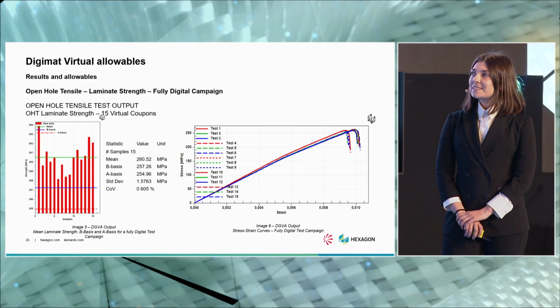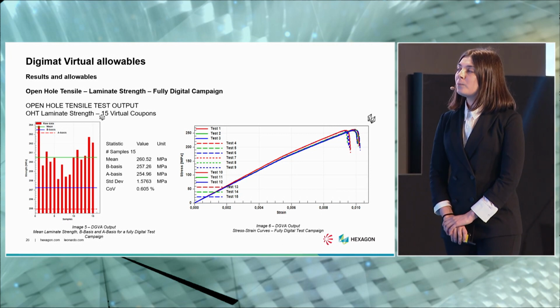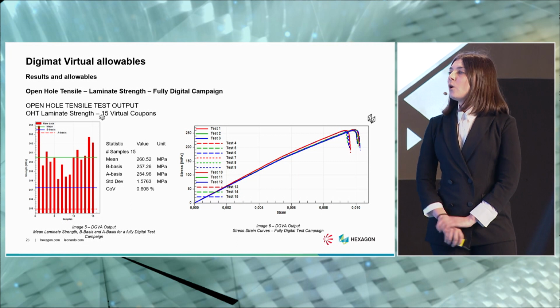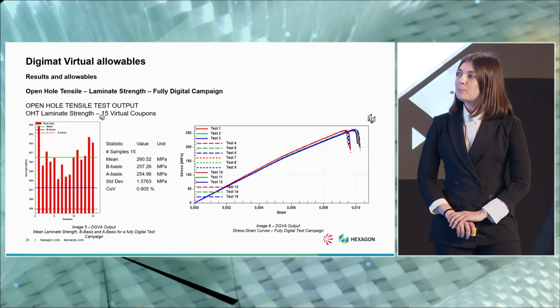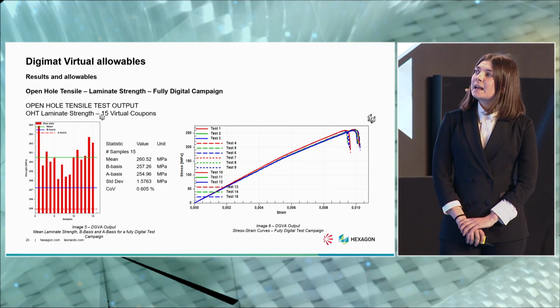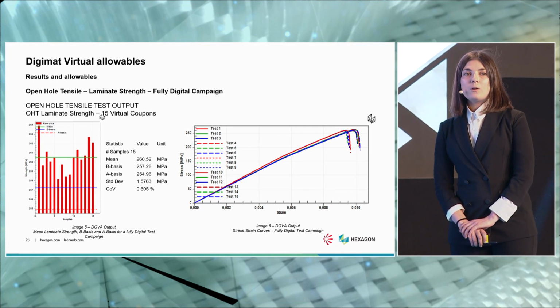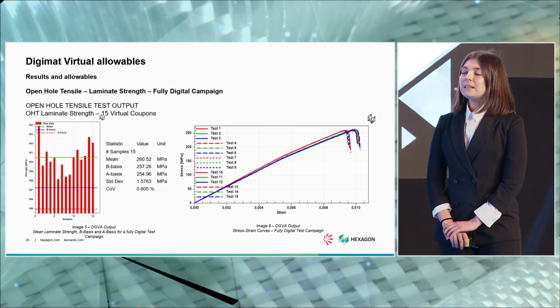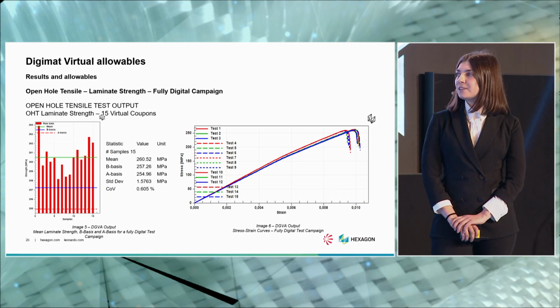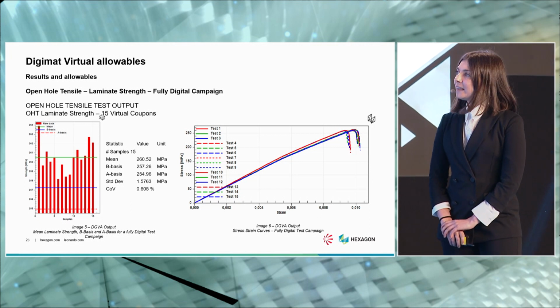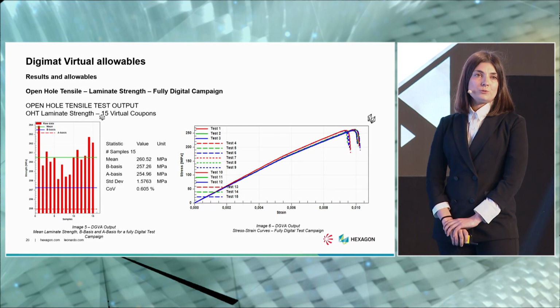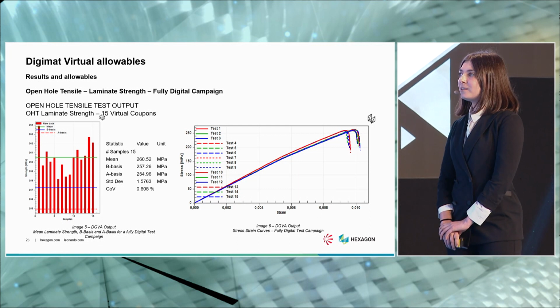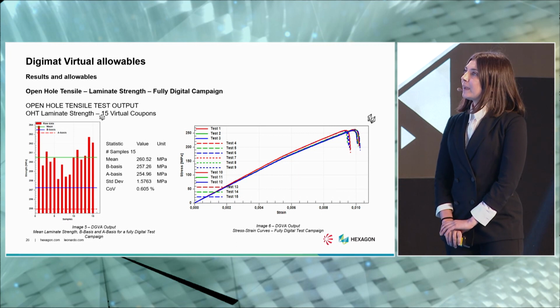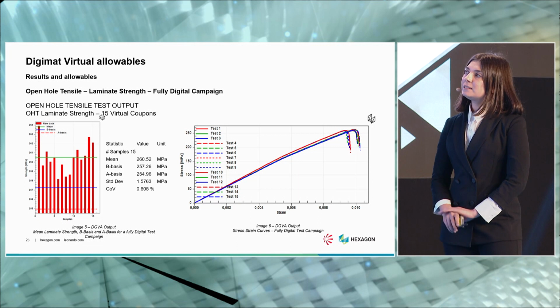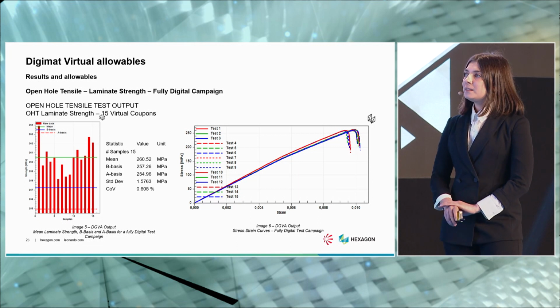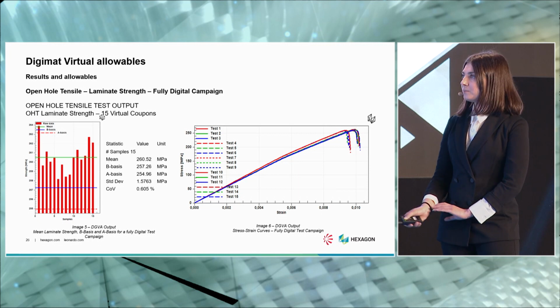Here are the results, the digital results from Digimat virtual allowables. On the left side, we have the bar chart of the 15 coupons and the virtual output of mean laminate strength, the B basis, the A basis, the standard deviation, and COV. And on the right part, we have all the stress strain curves of the 15 coupons overlaid. And okay, this is the fully digital test campaign with 3 batches, with 5 coupons each batch.